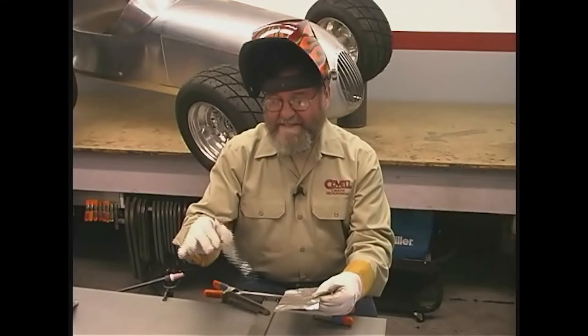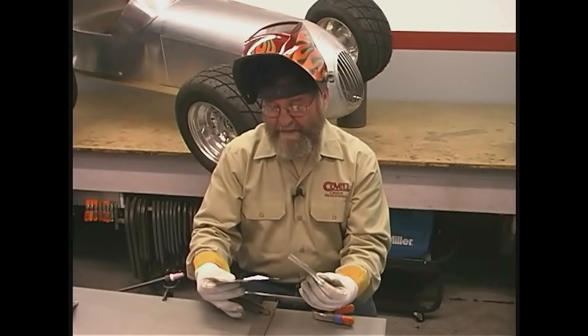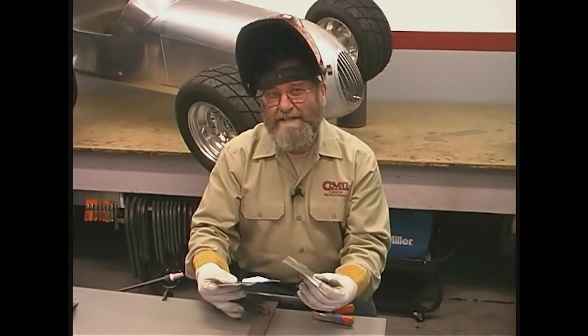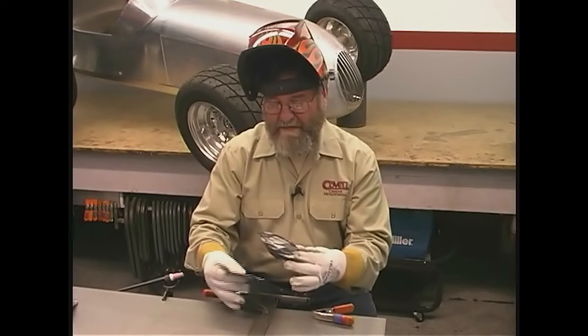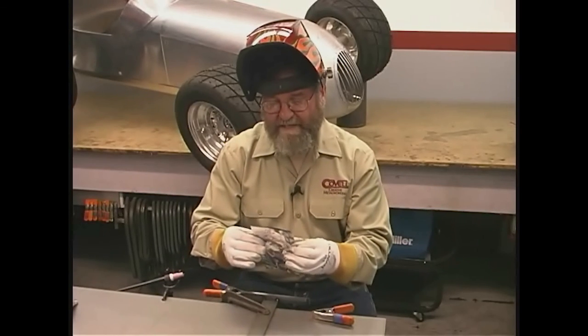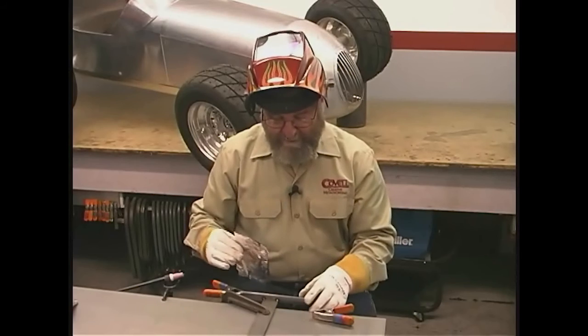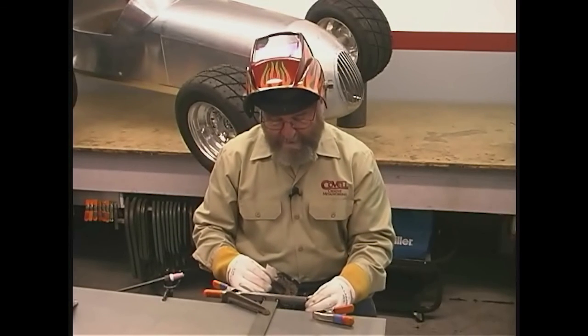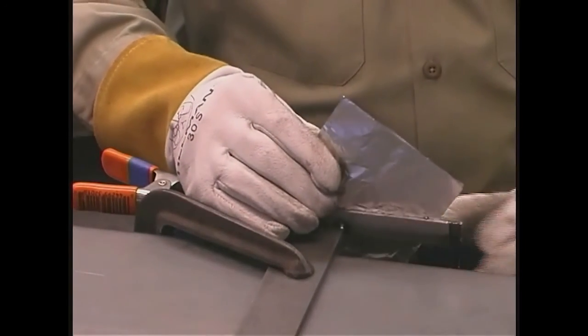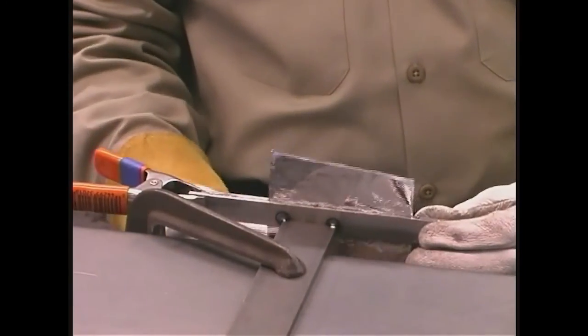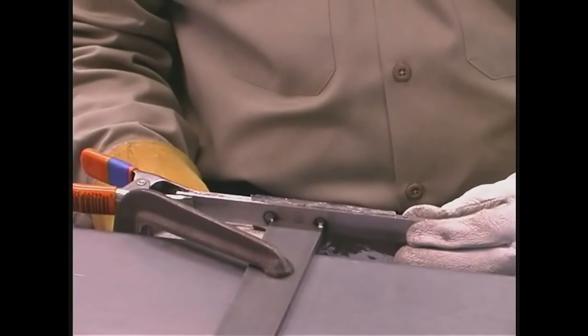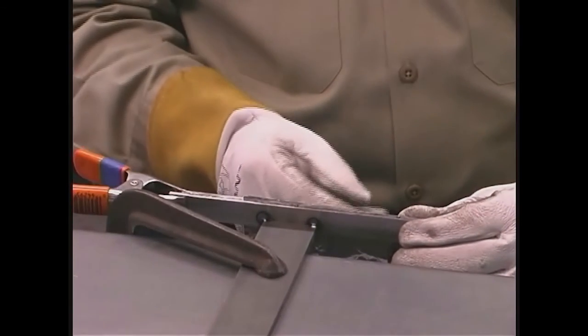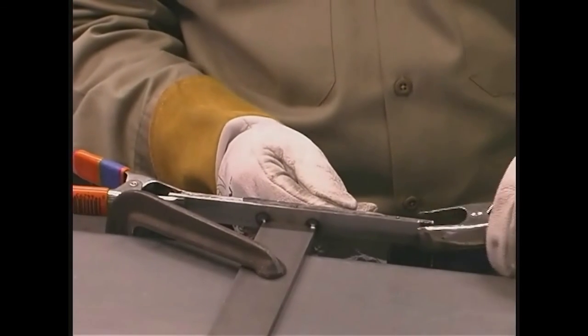Now we're going to weld some aluminum foil together. Now I measured this stuff and it's 1/1000th of an inch thick, and you might think it's absolutely impossible to weld. And this is kind of a parlor trick, but it can be done, and let me show you how. I'm going to lay one piece on top of another, and then I have a little fixture on my table here. This is just made from a couple of pieces of 1/8 inch thick material. So let me spread these apart, and we only want about 1/8 of an inch sticking up above the metal. The amount's not critical. And I'll put a clamp on this end.